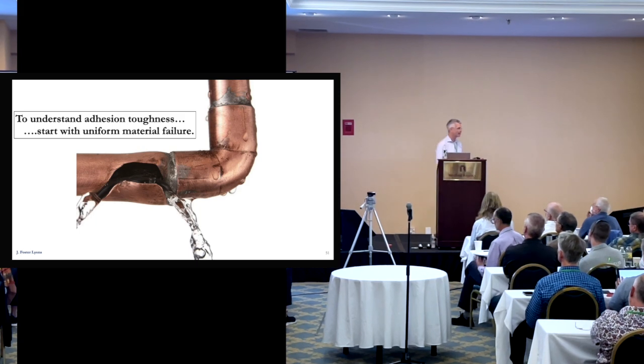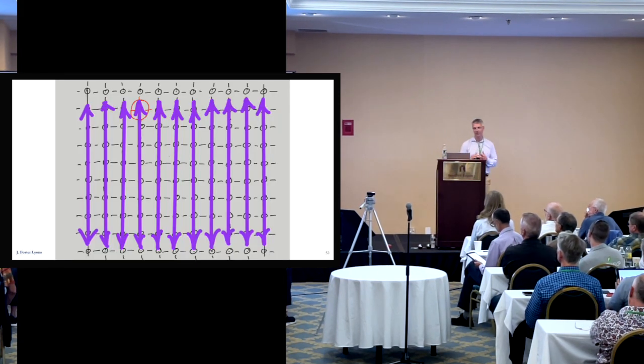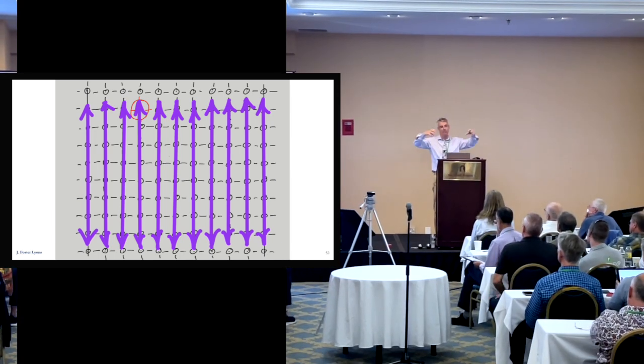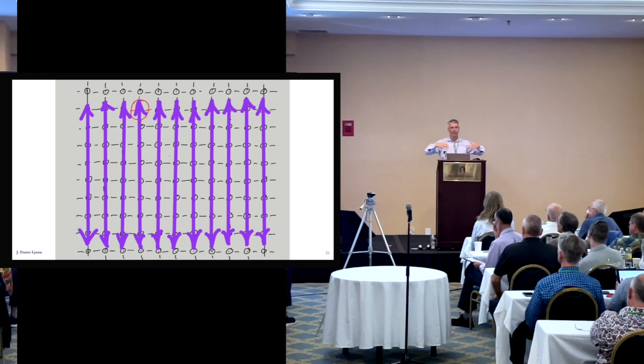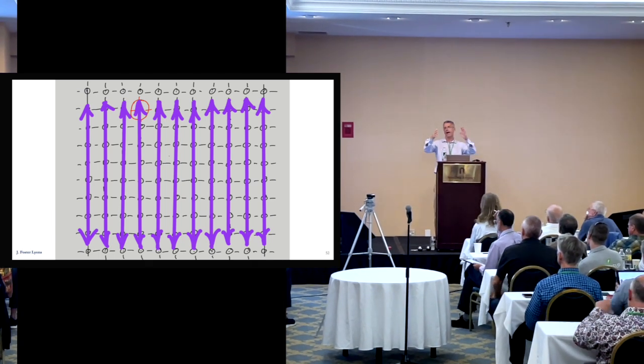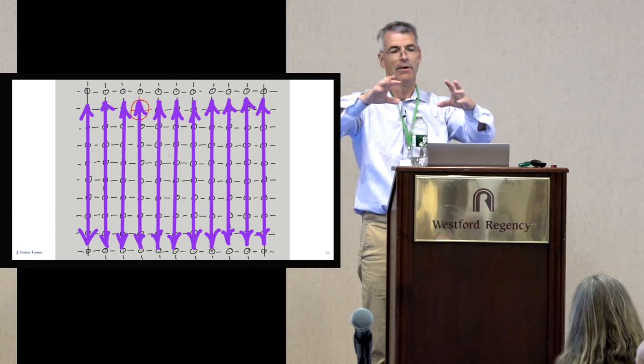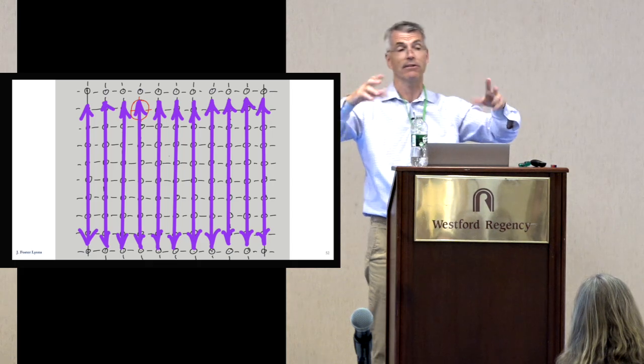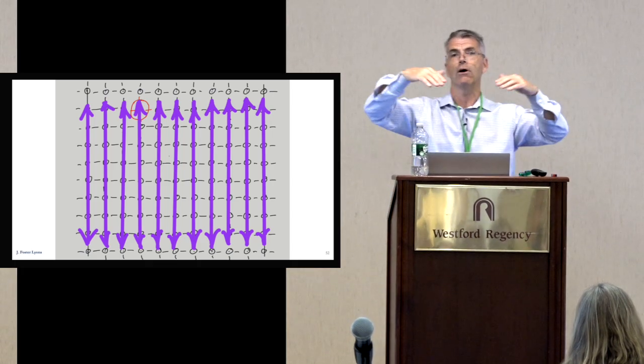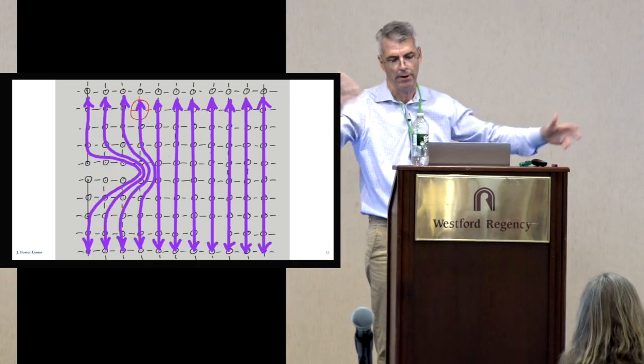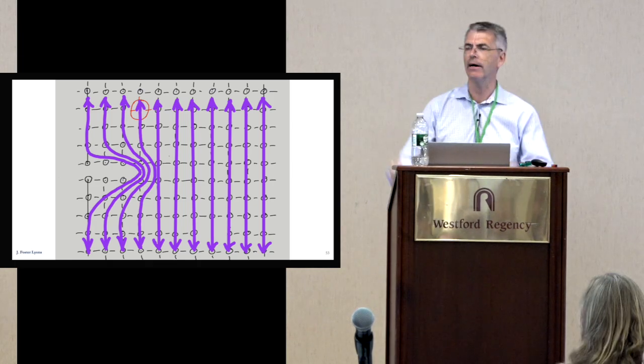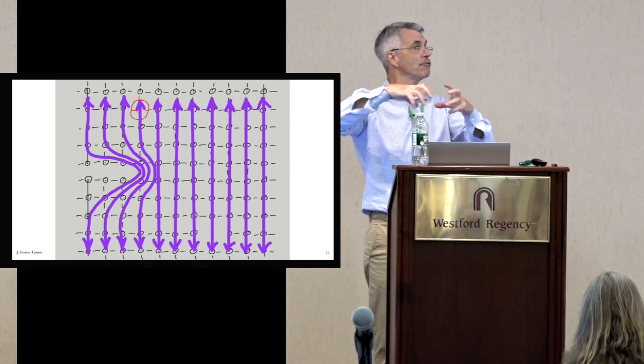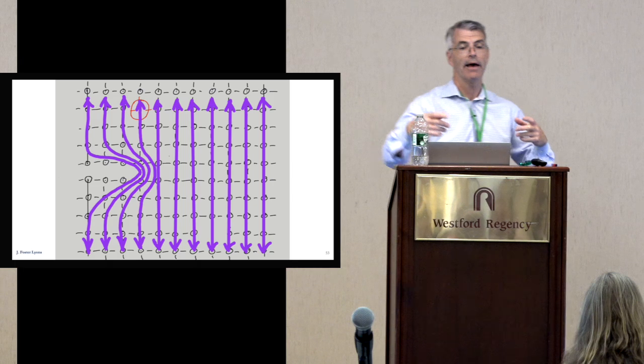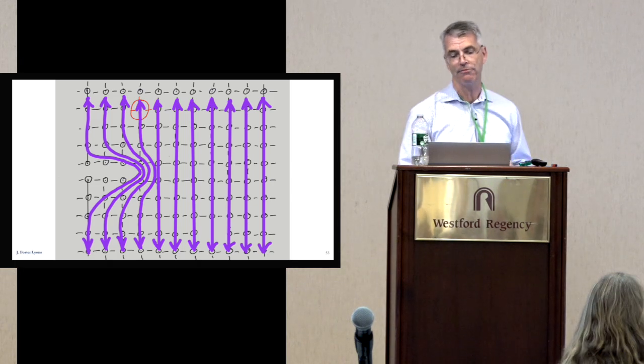So if you look at a three-dimensional material, this is a two-dimensional image of it, and you try to pull it apart, these purple arrows are the indication of the stress lines. You're trying to separate left from right. And the stress goes through all the atoms and through all the bonds between them. And if your material doesn't have any defects in it, any place you cut it, all the stress is uniformly distributed, okay? But if you have a defect and an edge somewhere, these stress lines start to concentrate at the point of the end of your defect, okay?